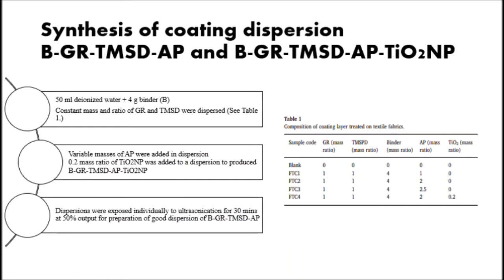So for the synthesis of coating dispersion, in a beaker containing 50 ml deionized water, 4 grams of binder was dissolved, and constant mass ratio of GR and TMSD were dispersed as shown in Table 1. And then variable masses of AP were added in the dispersion.